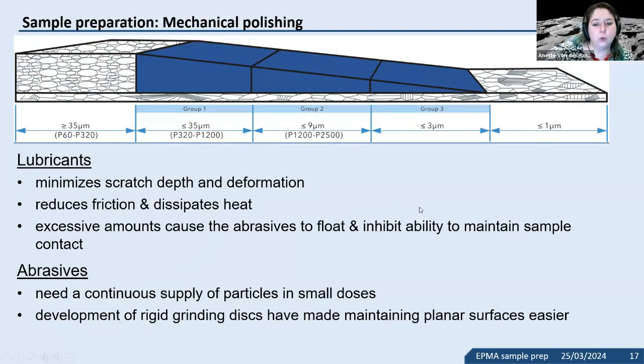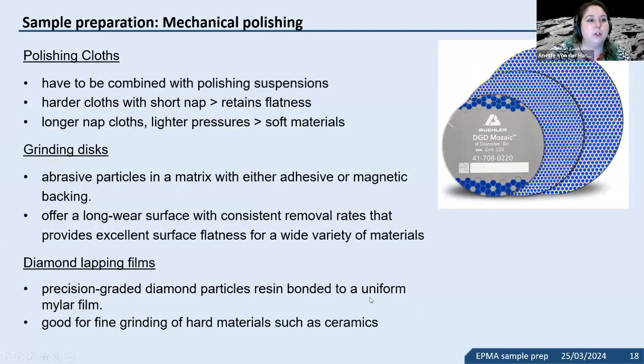Lubricants are usually used to help extend the life of the abrasives, but also minimize scratch depth and deformation. It also, if the sample is very sensitive to even minimal heat, can reduce friction and dissipate heat. So using some lubricants can be very helpful. And then there are different types of abrasive, either already as a liquid with some lubricant, or you can have diamond films or grinding discs, and they can be sometimes really good to keep a very flat surface without preferential polishing of harder and softer materials.